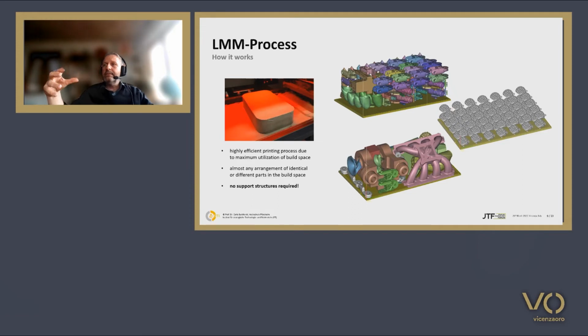And this means, despite we have such a small build chamber currently, which is about double the size of a business card, you have a highly efficient printing process because you can use that build space really to a maximum, because almost any arrangement of identical or different parts in the build space is possible because there are no support structures required. Due to this consistency of the material, this butter-like structure, it's supporting the parts that are directly below. So as you can see, you can make multiple layers of different parts or of the same parts at the same time.